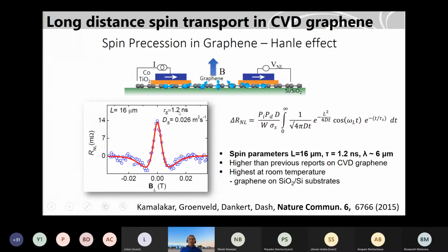And the spin lifetime is in nanoseconds. That's quite good for CVD graphene, because we have lots of defects and grain boundaries. This is also on a silicon oxide substrate, which can also affect the spin lifetime, because silicon oxide has lots of impurities, defects, and dangling bonds. So there is lots of inhomogeneity in graphene. In spite of that, you get spin diffusion over very long distances, up to 16 micrometers, and the lifetime is in nanoseconds.